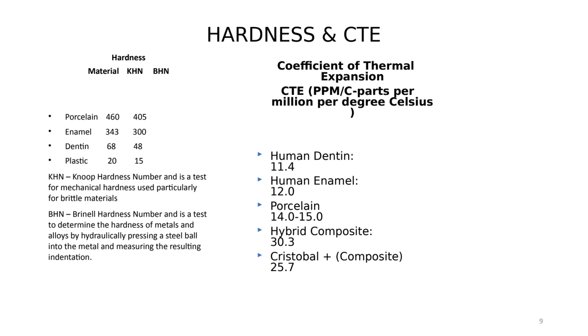For porcelain, the Knoop hardness number is 460, the Brinell is 405. For enamel, the Knoop number is 343, Brinell is 300. For dentin, Knoop is 68, Brinell is 48. For comparison, plastic is very weak, with a Knoop number of 20 and a Brinell number of 15.